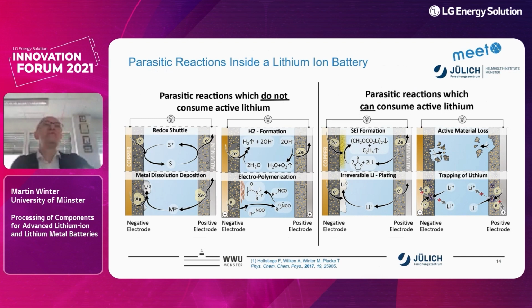But also we have parasitic reactions which do not consume active lithium. For example, redox shuttles, hydrogen formation. We have also metal dissolution and deposition, and also many additives, many electrolyte components that we are using do not consume lithium by forming SEI components. They only form a polymer without any lithium. That means electrons are consumed, but no lithium is consumed. So how can we differentiate between the electrons which come with lithium consumption and the electrons which are just consumed without any lithium loss? Because this finally tells us something about our lithium loss, and is also very important to tailor our pre-lithiation process of the cell, which is a processing step.